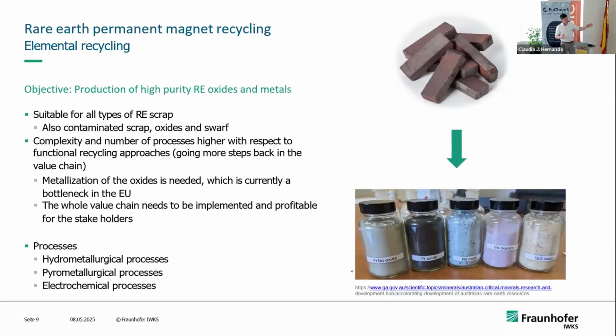And then we have the separated oxides. And like it was mentioned by Milan Groholz this morning, the metallization is lacking in the European Union. There's one company in the UK with 50 to 100 employees who can do metallization of rare earth oxides nowadays, but there is none in the European Union. So if you can produce these oxides, it doesn't mean that you can produce magnets, because the intermediate step of producing metals is lacking. And like we learned this morning, it's the most energy intense step, so most likely the least lucrative step to be performed.